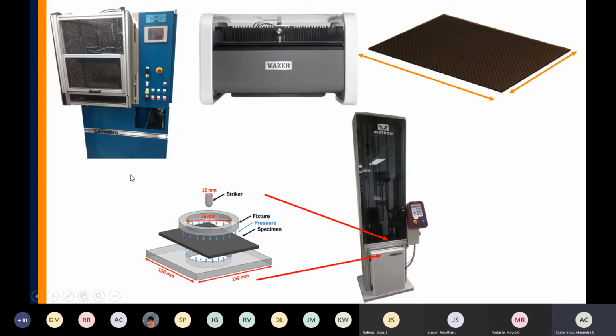This big blue machine that you see there is a compression press machine, in which we manufacture a composite. After our composites are manufactured, we use a water jet cutter. So we also have that in our lab. And then we produce, as you can see in this picture, the laminates exactly to the dimensions that we need for the testing. So with this new method that we're using, there is no reduction in the in-plane mechanical properties of the composite. And also we're increasing the impact damage tolerance in our composite.